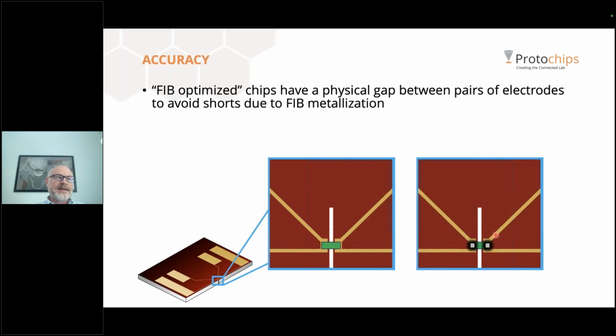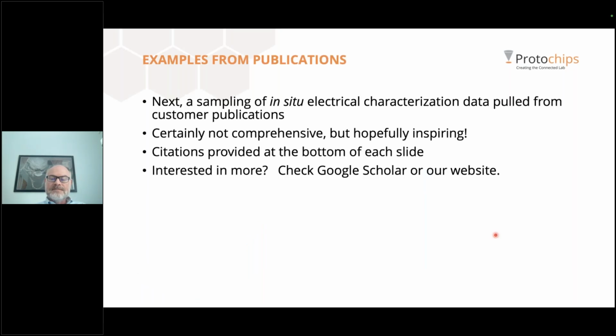There's a group in Europe that recently published results suggesting you don't need FIB metal at all. You can use van der Waals forces to form an electrical contact between the sample and the chip and mitigate leakage. And this is an interesting concept. So it assumes that the contact points on the sample align well with the contact points on the chip. So those are some of the considerations for accurate and reliable measurements.